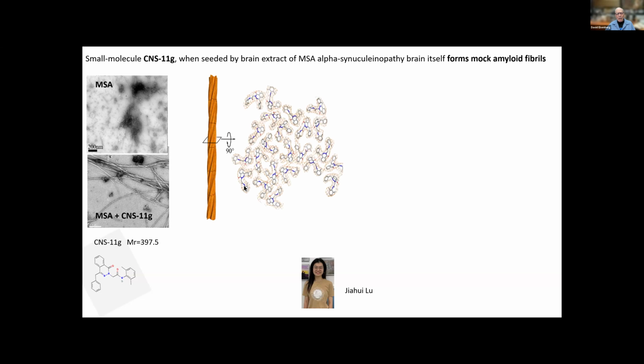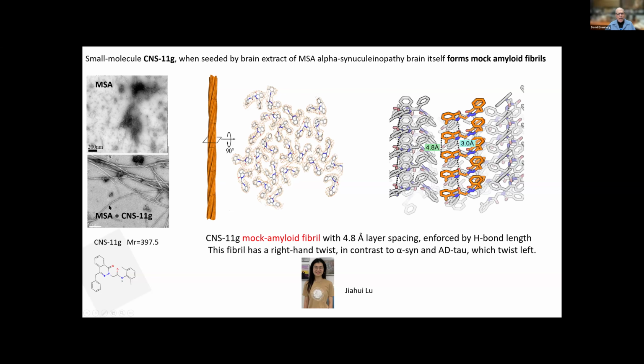And it turned out, to our amazement, that that fiber had a structure that's composed entirely of the small molecule. There's no protein in it at all. And this is a cross-section of one layer, and there are 23 protofilaments of CNS11G molecules stacked on one another. So it turns out it's a small molecule fiber. Also, I want you to note that it has a right-handed twist. That's important later on.